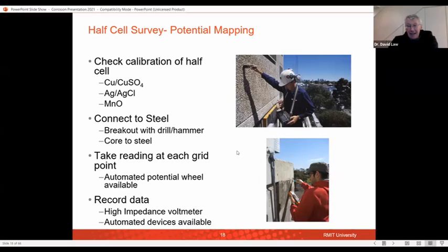To do these surveys, we need to have a connection to the steel. So that may well mean that we need to break out with a drill or a hammer, or we may need to expose the steel and make a connection to that. We then need to set up a grid on the surface so we can record it at set points. And these, we can see the people are putting them on at these set points on the grid, so we can build up a contour map. And we take points along there.